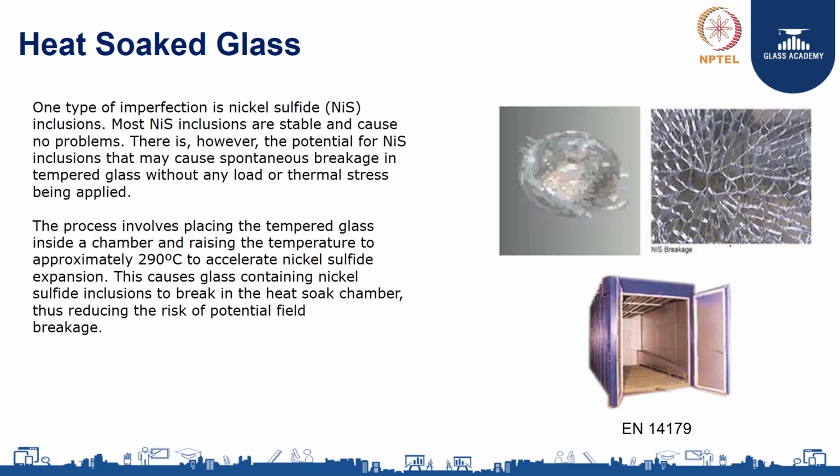If the glass has nickel sulfide, it will break in the chamber itself and can be recycled. If it passes the heat soak test, it helps the occupants by avoiding spontaneous breakage at any point in time, thus reducing the risk of potential field breakage in various places.